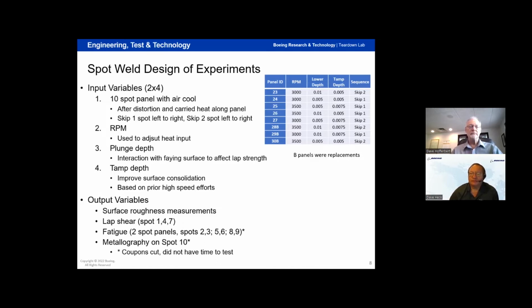So we used 4 variables. We either skipped 1 spot or 2 spots to let that heat dissipate as we were welding. And then we used the RPM to adjust the heat input. We looked at different plunge depths to see how far down we're going into the lower sheet. So that can affect both your lap strength, but also, again, how much heat you're putting into the surface. And then a tamp depth, which is, after the initial weld, you push down a little bit just to make sure everything is solidified and gives you a nice clean surface at the end.